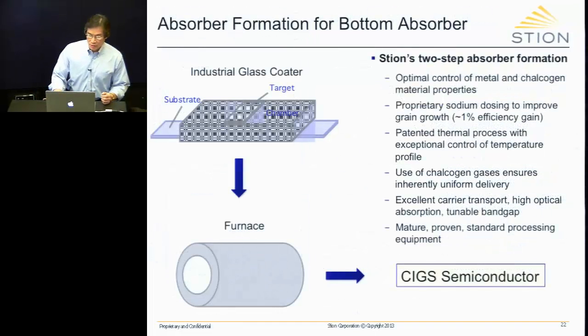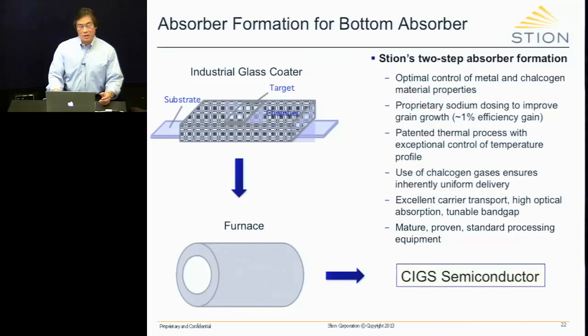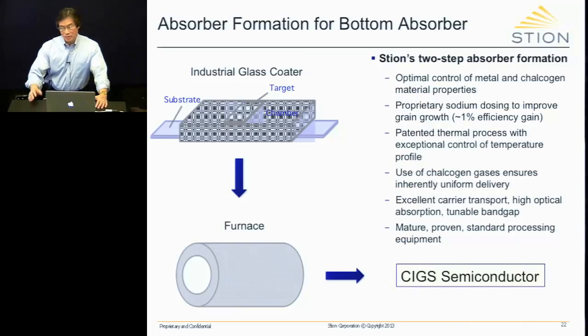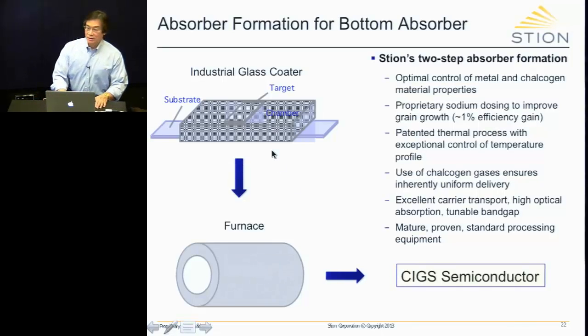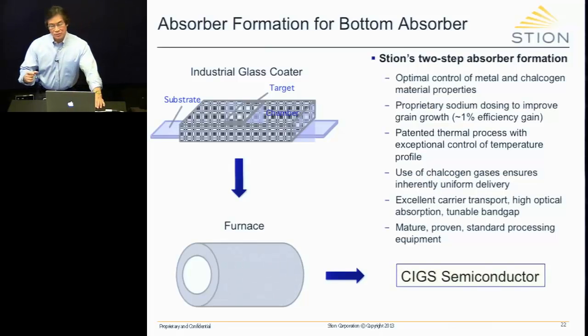So what do we do for the bottom device for normal CIGS? We do, which I'm sure you're familiar with, a 2-step absorber formation process. We use standard equipment. We sputter down metal precursors: copper, gallium, and indium. In fact, we don't sputter gallium per se. We alloy that with copper to make a copper-gallium alloy. We sputter that down, and then we sputter down the indium. And this way, the stoichiometry is determined solely by the thickness of those layers.